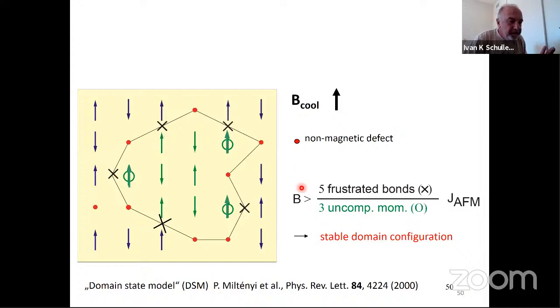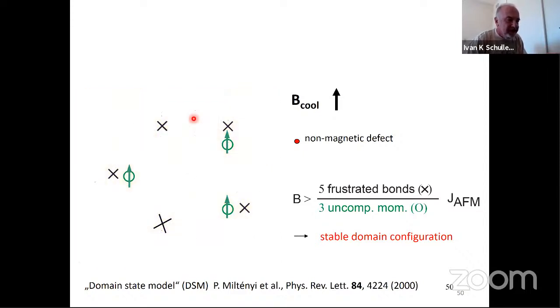So if you have, let's say, five frustrated bonds and three uncompensated moments because of the defects, then you see here you have some frustrated bonds, some frustrated bonds there. See, this spin points up and this one points up. It doesn't like to do that, but because there are defects, it can do that. And so if you look, you eliminate all the uncompensated moments there. There it is, all the uncompensated moments eliminated.